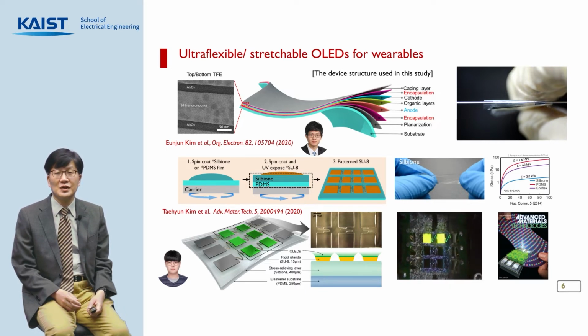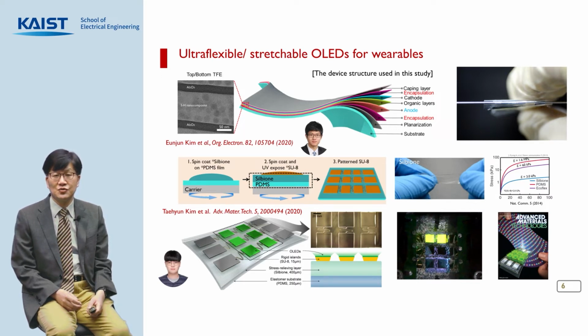Furthermore, we have recently demonstrated stretchable OLEDs so that OLED patches can accommodate body movement. Combined with serpentine-shaped interconnecting electrodes, a stress-relieving layer based on a low Young's modulus material called Silbione led to highly stretchable OLEDs, the interconnecting electrodes of which can be stretched up to 140% with performance comparable to conventional rigid devices.